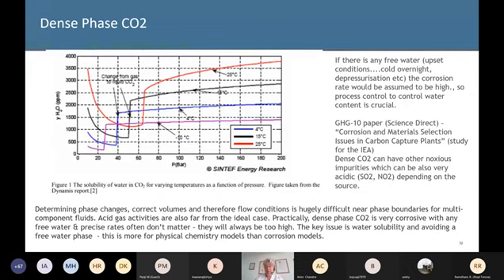Bear in mind that dense phase CO2 can have other impurities that are also very acidic, so you have to look out for those. And it's very, very difficult to monitor and to model this, and fundamentally the issue is that you've got to be looking more at process control. It's more about physical models than corrosion models. It's about controlling your water content here.